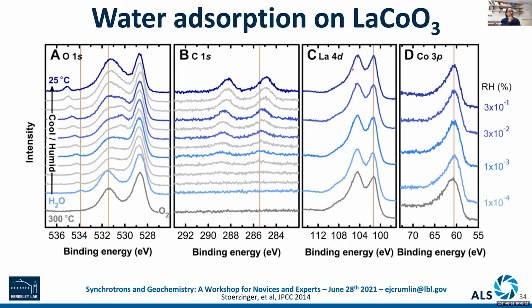Here is another example on a different system. This is lanthanum cobaltite, but here we're showing more clearly the type of spectra you might be able to observe. This is collecting the oxygen 1s, the carbon 1s, the lanthanum, the cobalt. So we're getting all the elements of this oxide. We're changing the temperature. We're keeping a constant humidity in the background, or changing the humidity depending on how the temperature is there and the pressure that's there. And we're able to see how the different water species, and in some cases carbon, is interacting with these surfaces. So we're able to get really, for the first time, this really clear insight in terms of what is going on to the surfaces and the interfaces under these active environments.